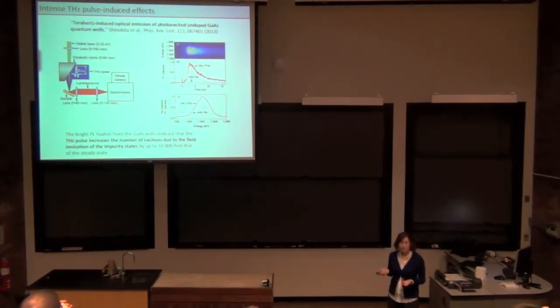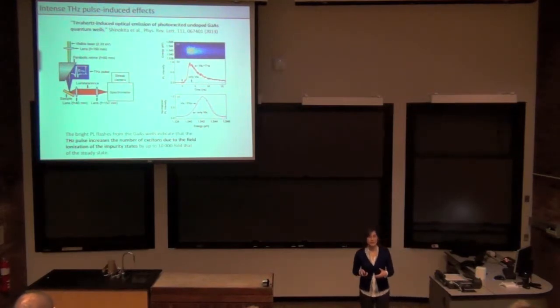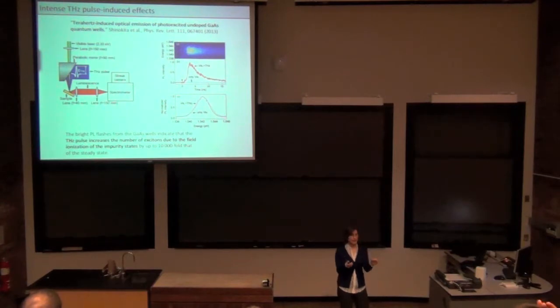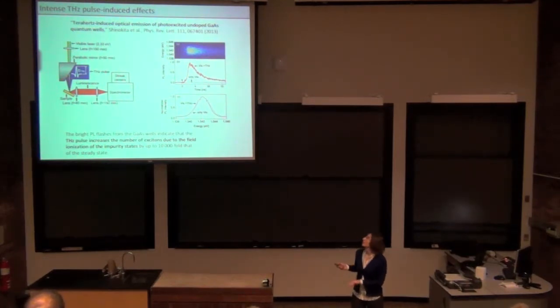What do they think is happening? Well, the optical excitation generates carriers. Many of them go into some sort of defect trap states. What the electric field of the terahertz pulse does is ionize all those carriers, sort of flushes them out of those impurity states. And now they can form excitons and recombine radiatively. So that way they can turn on the optical emission or significantly enhance it.